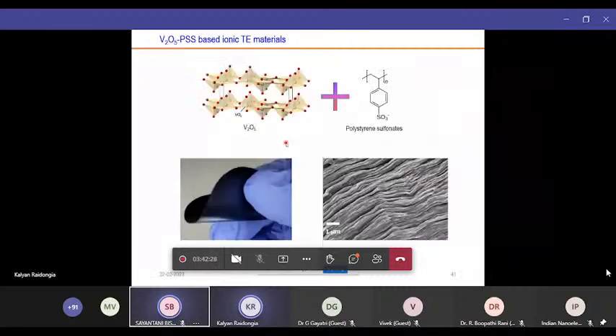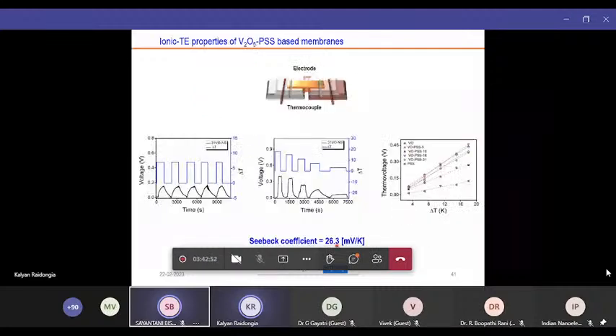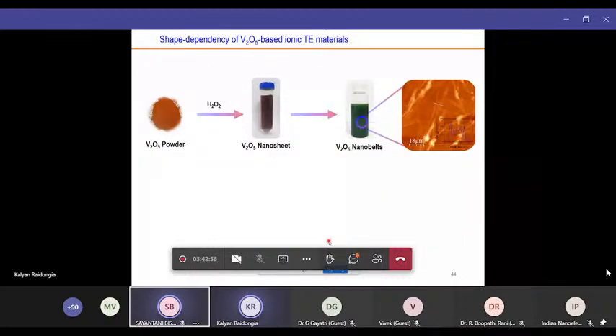Another important property of 2D materials is that we can easily tune their nanochannels by functionalizing with different kinds of materials. So we functionalized these V2O5 nanochannels with PSS polymer. Then we can again prepare a membrane and do the necessary characterization. Now we can see that the Seebeck coefficient is increased to 26.3 from 14, which is an increase. So like that, we can do various composition analyses and different experiments.